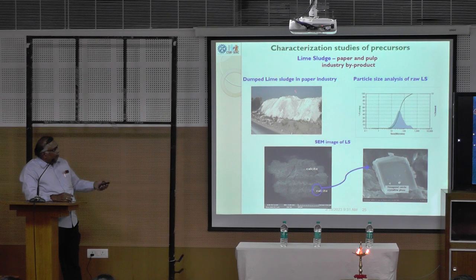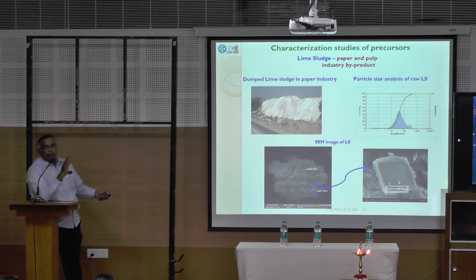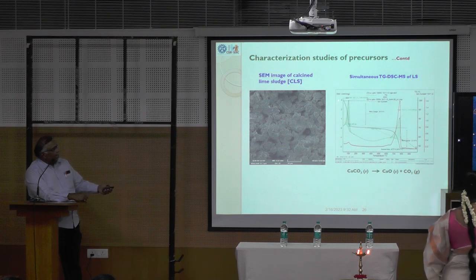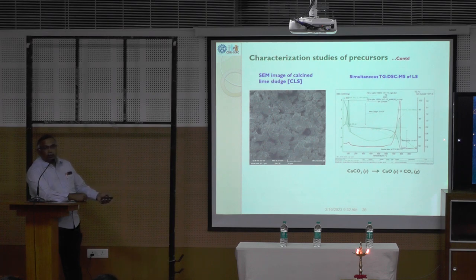This is the structure as received — this is the scanning electron microscope image of lime sludge (LS). I found that this is nothing but calcium carbonate — that is calcite. Lime is the parent material for cement, because burning lime gives CaO. When I am heating this, I am heating the lime sludge — because it has a lot of moisture, that is getting removed. Then there is a mass loss of up to 50 percent. What happened is this calcium carbonate, when burned, forms CaO and releases CO2 — carbon dioxide. That red line is the CO2 peak.